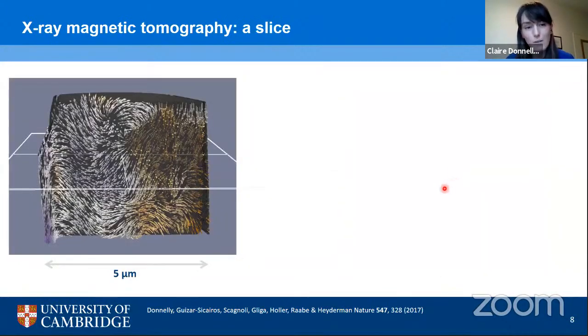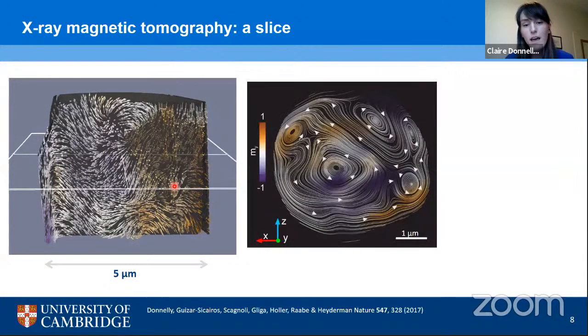So in order to take a closer look, we first of all look at a two-dimensional slice of the magnetization. And in this slice, we take a closer look by plotting the in-plane components with these streamlines. And the out-of-plane component is indicated by the color. So purple and orange represent in and out of the plane. Now, when we see this configuration, we can notice a few quite striking facts.